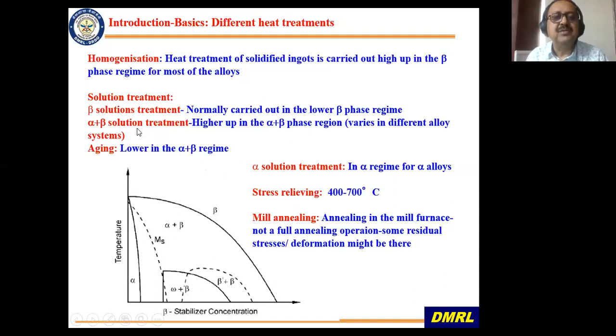Then you have what is known as alpha plus beta solution treatment, that is done higher in the alpha plus beta region, somewhere in this region, okay, in this pseudo binary phase diagram, somewhere here, depending on the alloy, slightly higher up in the alpha plus beta region. Then when you want to age an alloy, normally it is done lower in the alpha plus beta region. That again varies from alloy to alloy. It can be anywhere from 450 to 700 degrees centigrade.